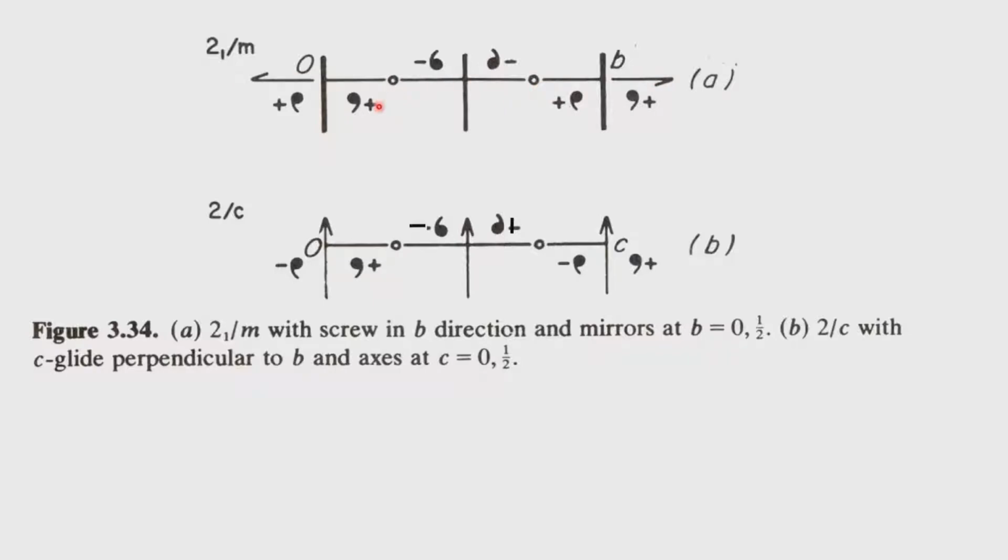So, this therefore gives us the 2 1 by m symmetry, and this is where we have to be cautious in deciding the equivalent points, because the equivalent points now will change their phases, in the sense that if we have the 2 1 by m operation here, the mirror operation, using this as the origin, will take x y z to x y bar z.